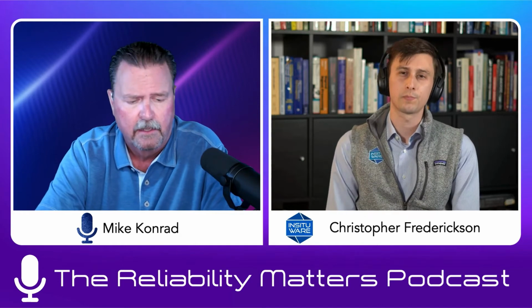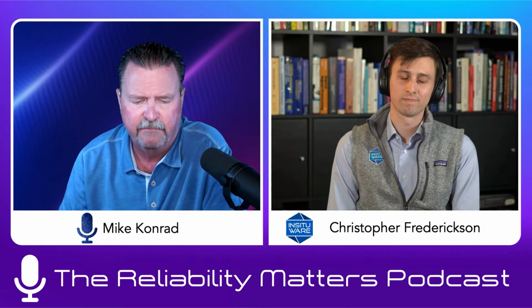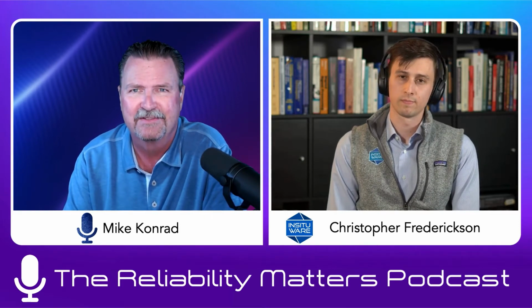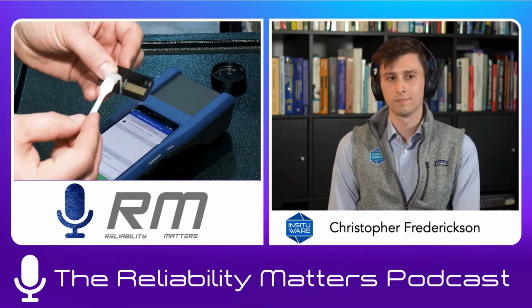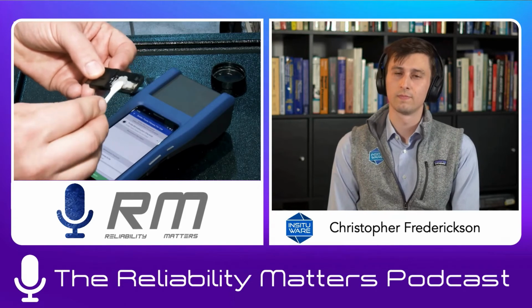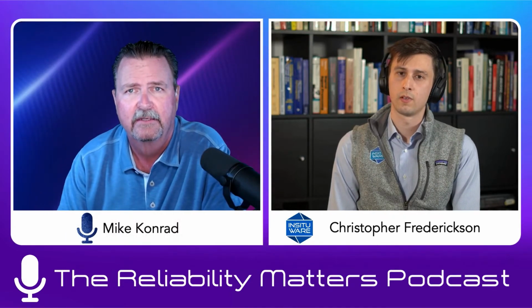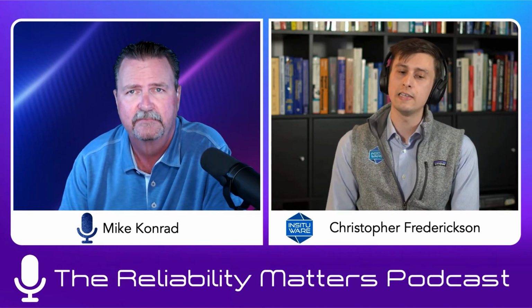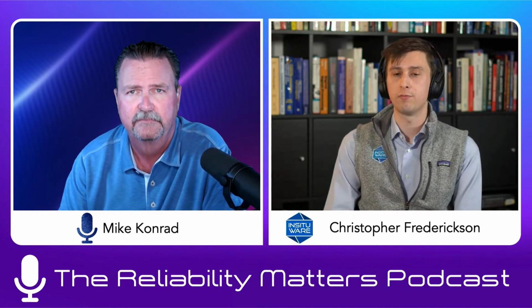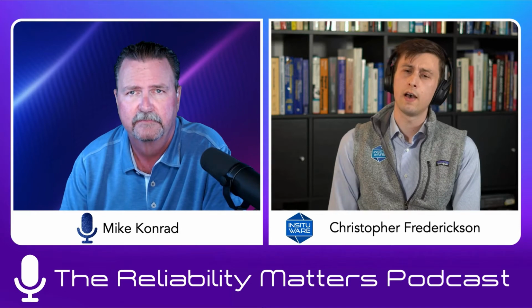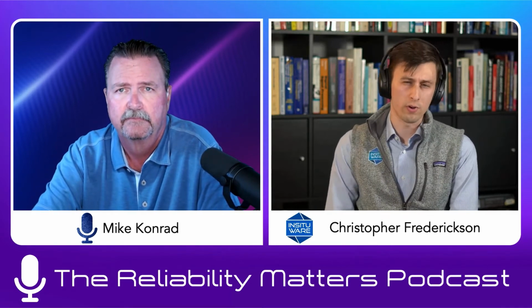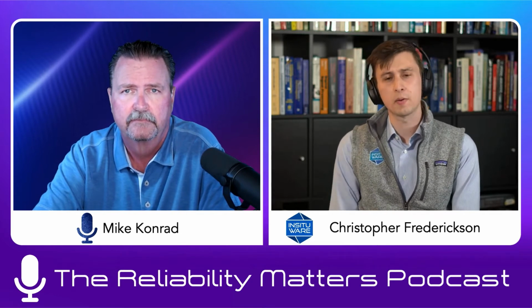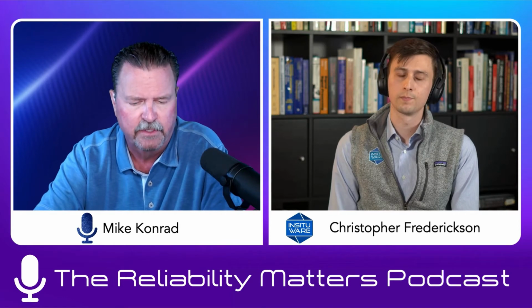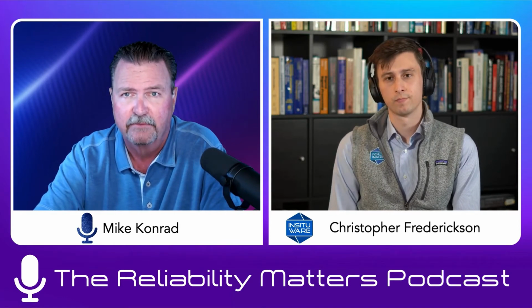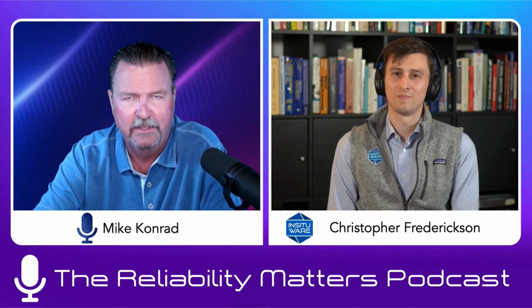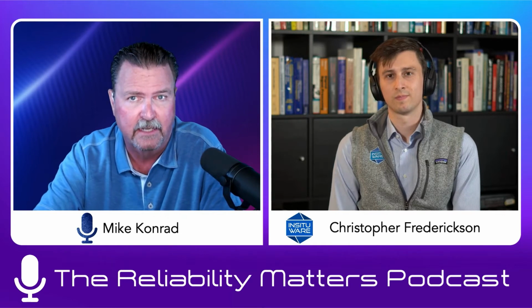I don't want to get into your pricing model, but I'm just curious, does every test consume a part? Going back to that video, that little part right there, is that used one time or is it cleaned off and used again? For the solder paste measurement, that coupon is reusable. You can clean it off and reuse it, our recommendation is up to a week, before it starts to degrade the gold coating on the surface. So that's reusable, but it depends on the specific measurement that we're making as well. There are cases where it can be reused for a week or so, and other cases where you need a fresh test coupon or cartridge, whatever it's called, each time, depending upon what they're testing for. Is that the correct assessment?